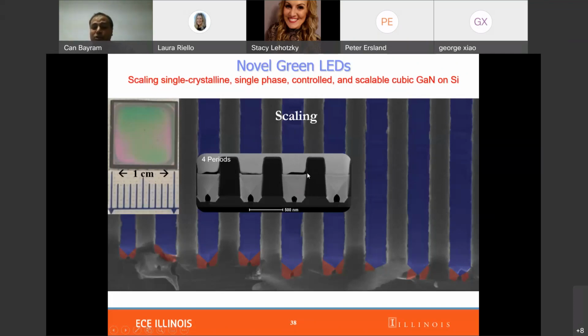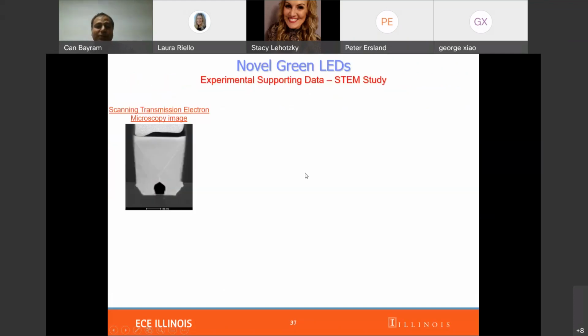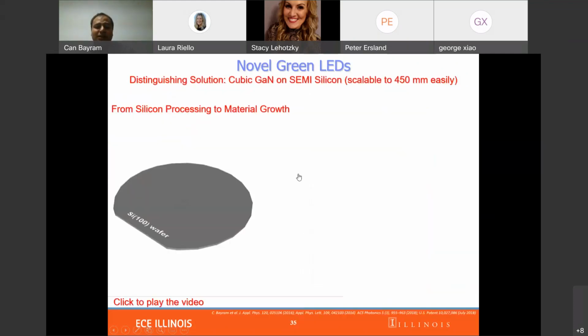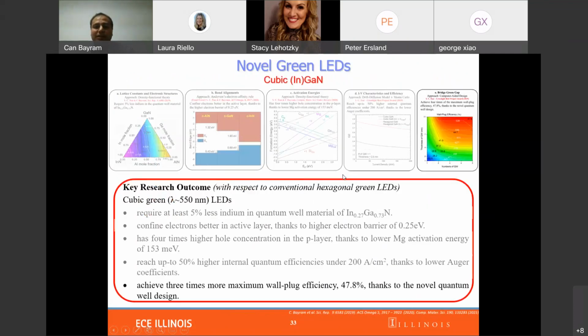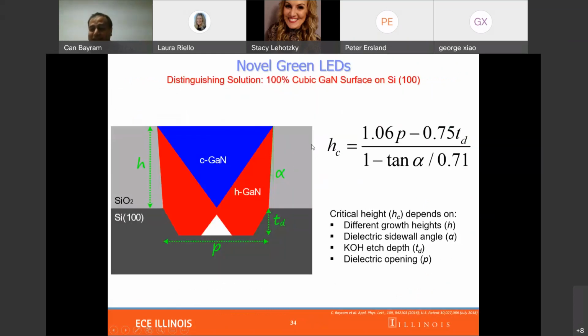The oxide should not go above your pattern. That's where this formula, which tells you how thick your oxide should be, is critical. Right now, for example, we are looking into ways to grow this through removing the oxides, and we have already mostly succeeded and have a couple of patent applications.